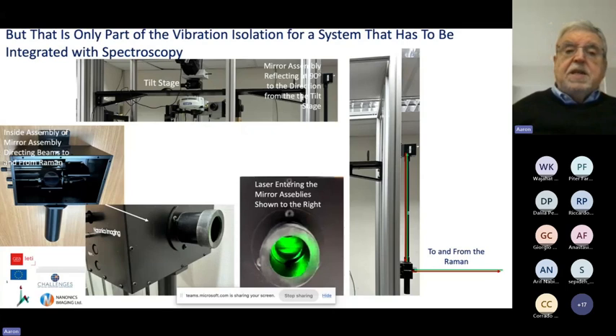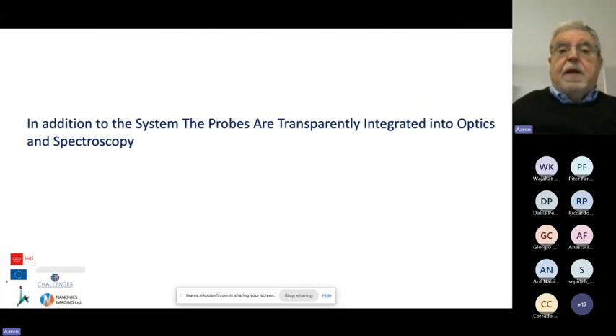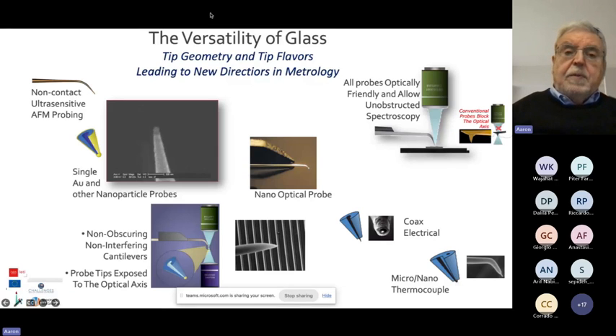So in addition to the system, we prefer, although you don't have to, probes that are transparently integrated into optics and spectroscopy. So we prefer probes made out of glass that we put a lot of effort into, and we've incorporated into this system. This is an AFM probe. It is completely transparent, okay? This is a glass-based plasmonic probe. And I don't know if you can read, this is 100 nanometers. This is less than 100 nanometers, and it's a gold nanoparticle on the system.